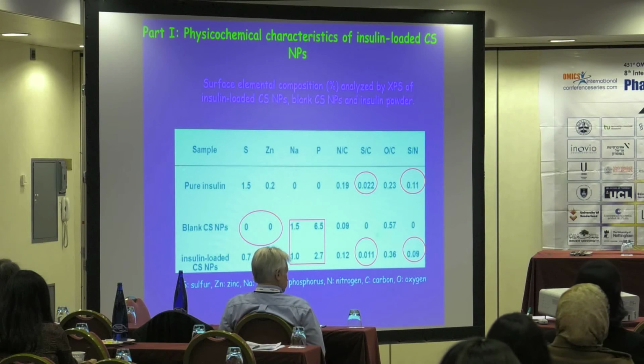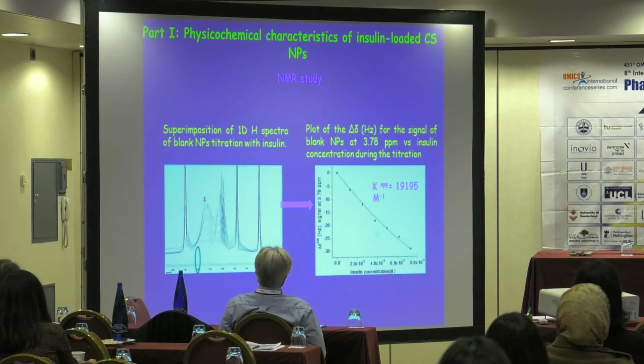Not all of the insulin, but a proportion, because the ratios are higher in the case of pure powder insulin. To confirm this means we have weak binding, with a proportion adsorbed on the surface, so we conducted another experiment.